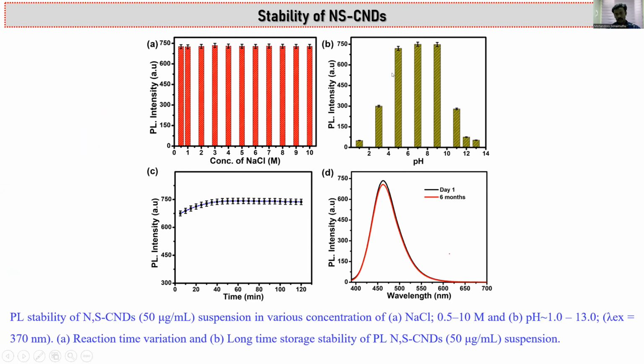This is very important for biological applications, since stability in acidic or basic medium is not good for biological application. Here we get the highest stability from around pH 5 up to pH 9. Also, reaction time variation causes very little change in the photoluminescence intensities. We also measured the photoluminescence intensities from day 1, and after 6 months the stability is 99%, with no changes in the stability of these carbon dots.